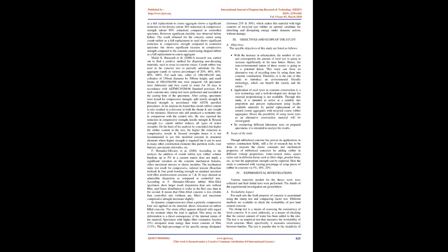Some drawbacks were also reported, such as the large decrease in compressive strengths and the increase of water requirement and air content. The test results demonstrated that rubberized concrete mix possesses interesting properties that can be useful in structural and non-structural applications. The test results also show that the performance of concrete is significantly affected by the type and content of the rubber particles as well as by cement type and admixture properties.